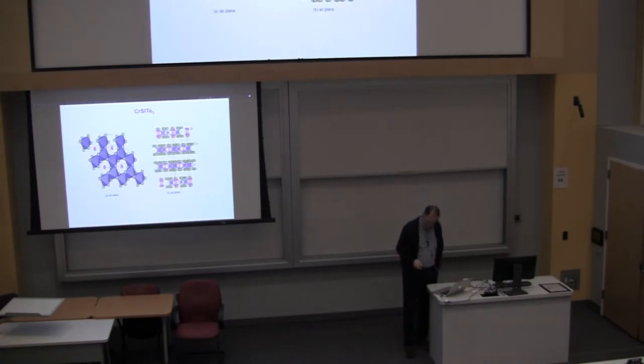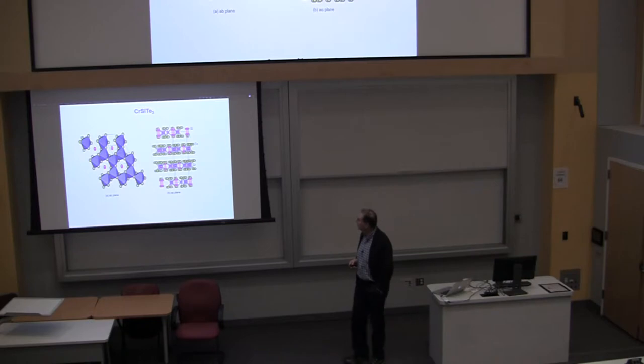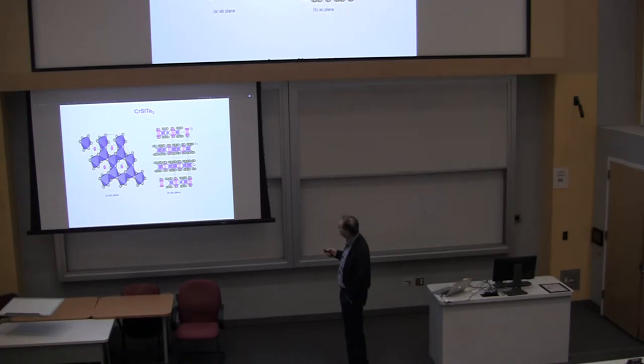And so you can have a magnetic layer with a van der Waals gap. An example of this kind of material, one we looked at a few years ago, is chromium silicon tellurium 3. This is a good example. It's a ferromagnet semiconductor, very two-dimensional, cleaves easily. So you've got a layer of chromiums. These are silicon dumbbells. That's why you'll often see these written as 226, because you're trying to express the fact that you've got these silicon-silicon bonds in there.